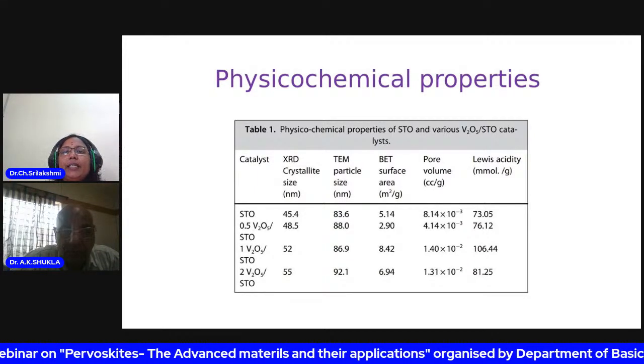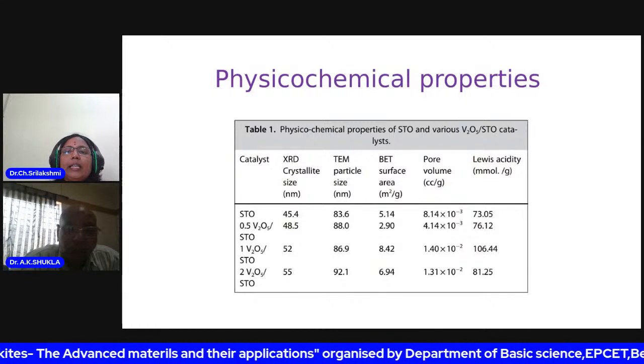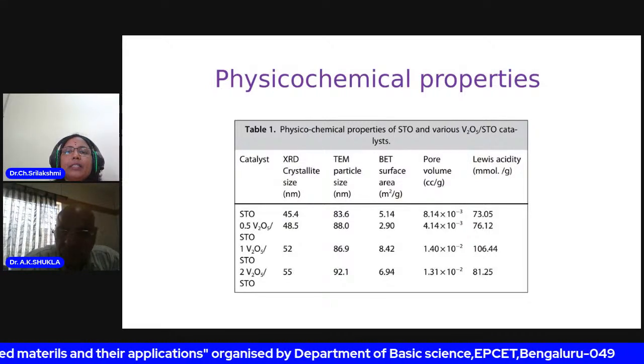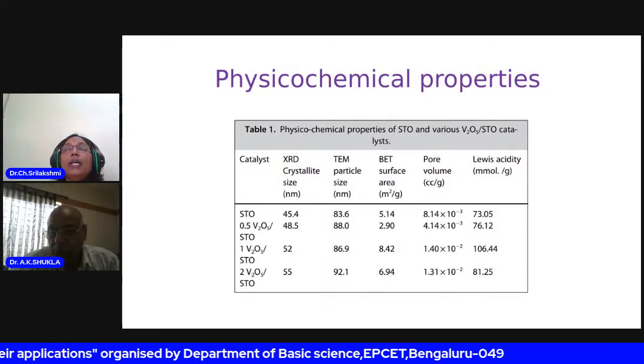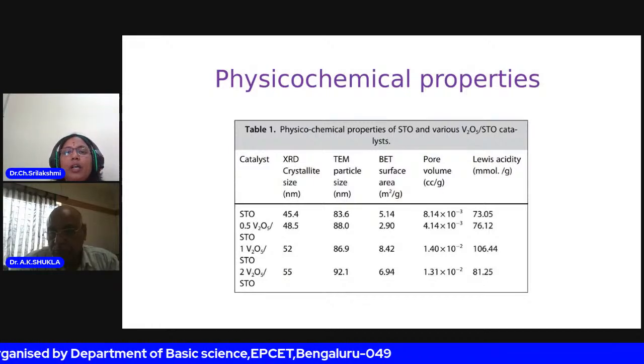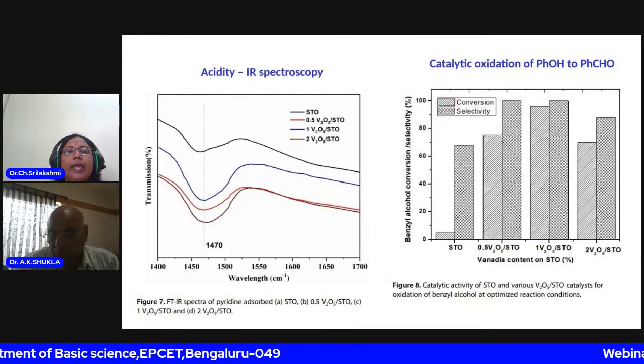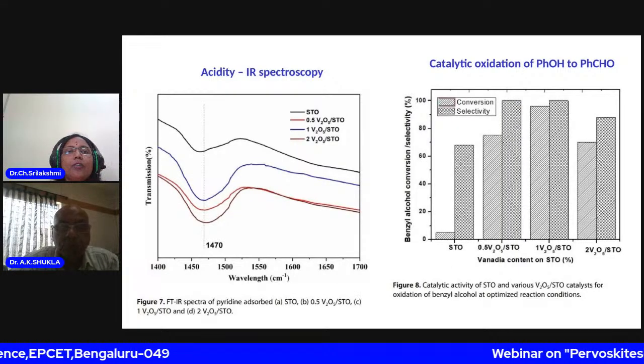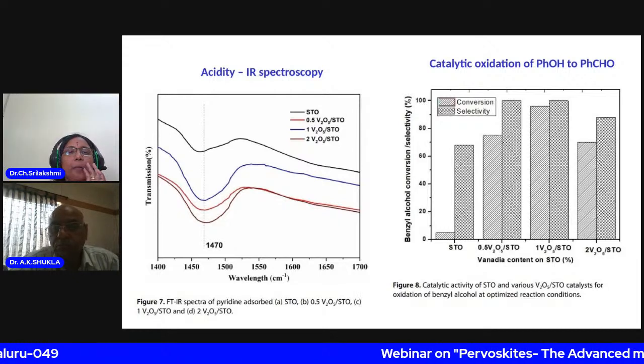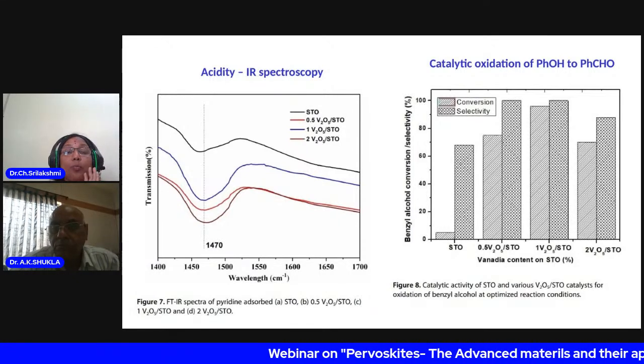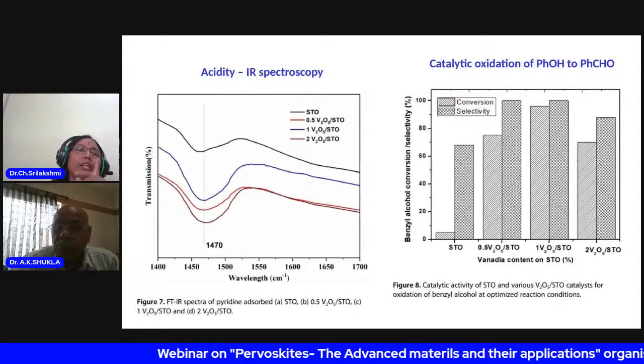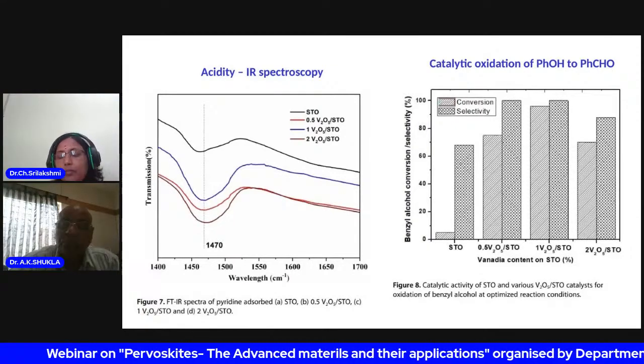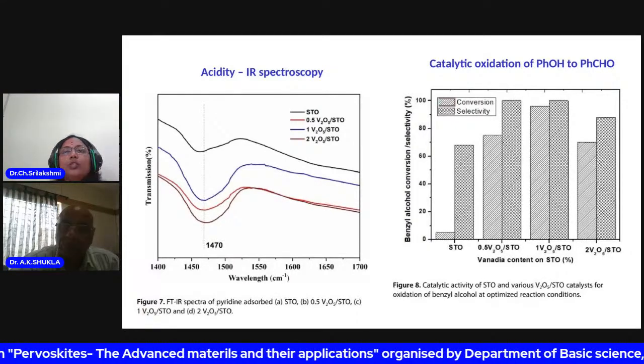So Lewis acidity, you can see Lewis acidity is increasing until 1 weight%. After that it goes down. This is due to change in morphology of the samples. So again, you can see the Lewis acidity is confirmed. Only Lewis acid sites are present in the sample, but not Bronsted acid sites, even after incorporation of vanadium on the surface of the strontium titanate.